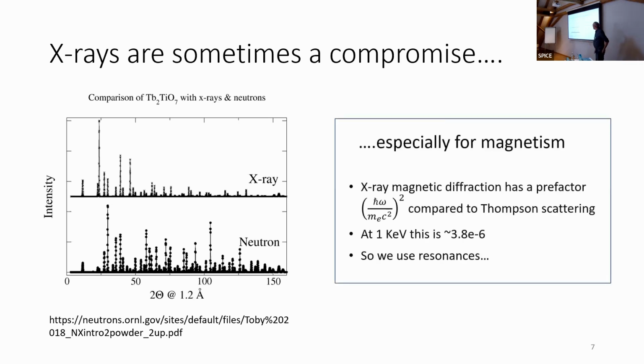It's even worse when you work with magnetism, because the diffraction peaks that we saw before that appear below the Néel temperature get this prefactor in their intensities when you work with X-rays. This is on the order of 10 to the -6, which means that magnetic diffraction peaks are typically 6 orders of magnitude weaker at the energies we typically want to work at with synchrotrons.